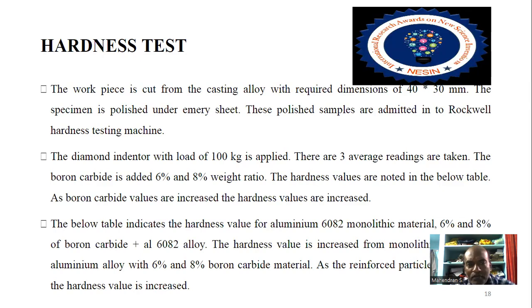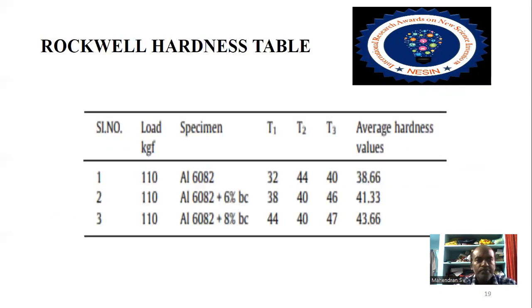As the boron carbide content increases, the hardness values increase. The below table indicates the hardness value for aluminum 6082 monolithic material and with 6% and 8% boron carbide. The hardness value increases from monolithic aluminum to the aluminum alloy with 6% and 8% boron carbide. As the reinforced particle content is increased, the hardness value is also increased. These are the main noted points.